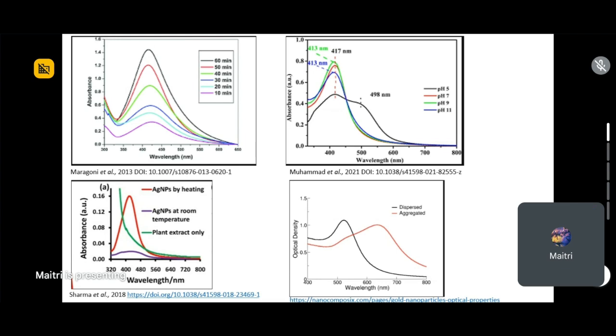Then over here, the same thing is happening, but here they are doing it for pH. So just say pH 11 gave me a nice okay absorbance. pH 7 and 9, like red and green, they are good, out of which pH 9 is like the best. It is giving me the best OD reading. But pH 5 is causing some trouble. What is that? pH 5 is causing almost a deterioration of my AGNPs. And how do I understand that? The peak over here is becoming a plateau over here. So, a deterioration of the peak helps me understand that my AGNPs have deteriorated, they have probably disintegrated, the number